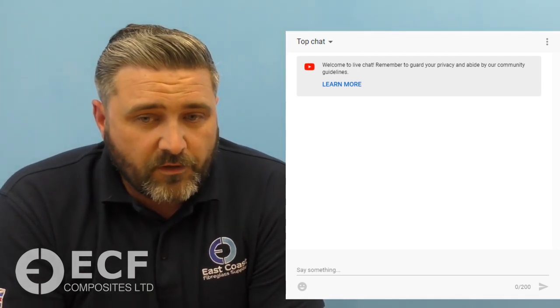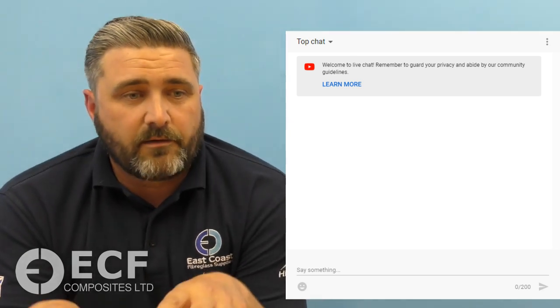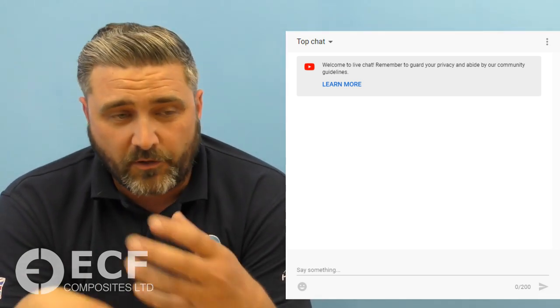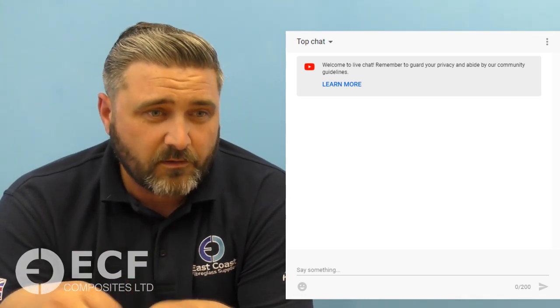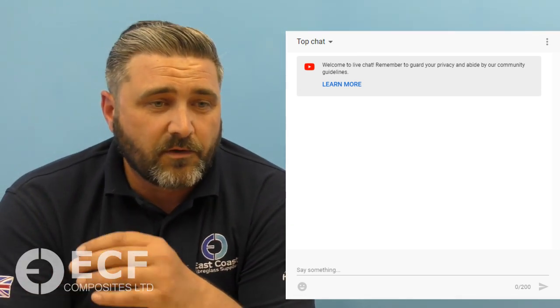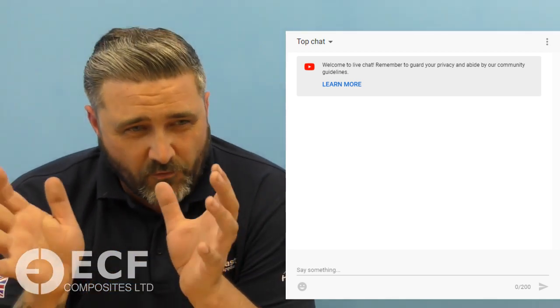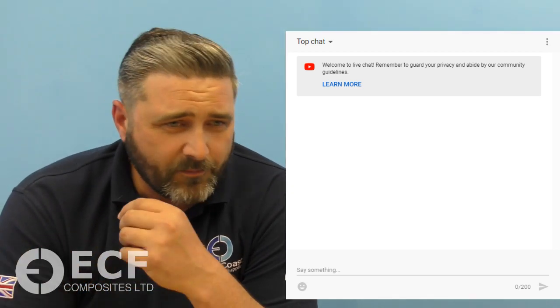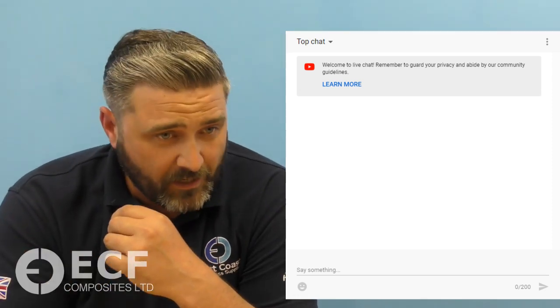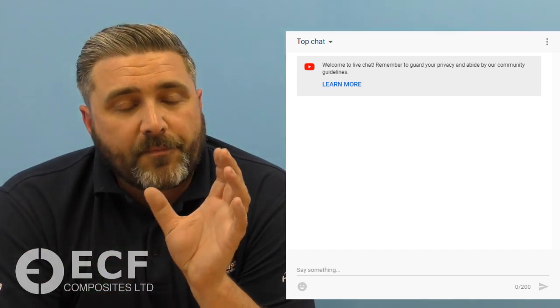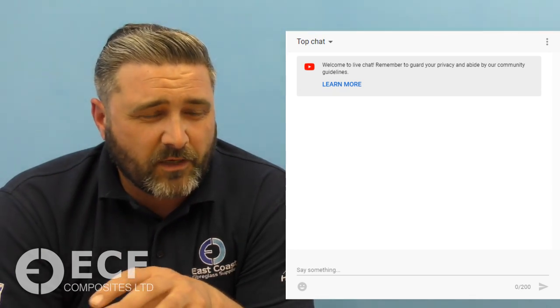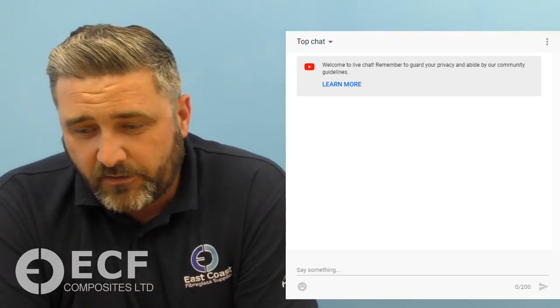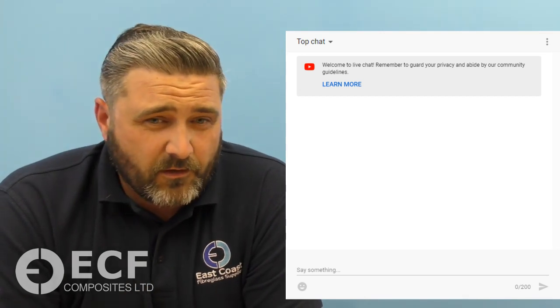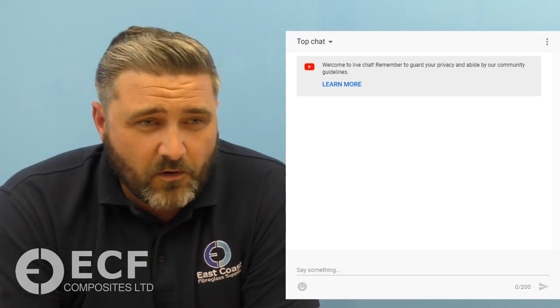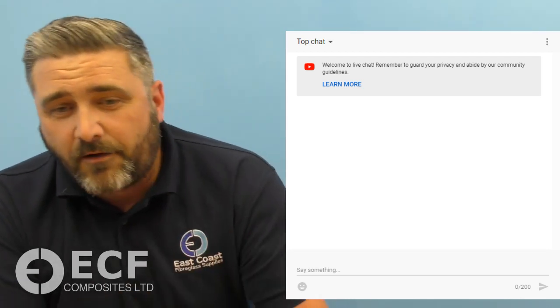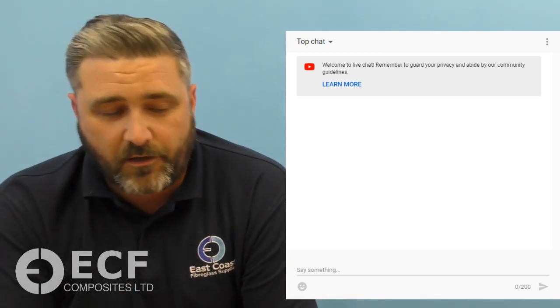Also, if you're going to re-flow coat an area, bear in mind that it is an old laminate. You're not going to get 100% chemical bond between that and an old material. So it's a good idea to give it a really good heavy sanding, wipe it down with acetone to promote some chemical adhesion back, and then go on with a flow coat. But let's say that chemical adhesion is not going to be 100%. That's sometimes why you get a lot of conflicting advice and arguments online on forums. People saying you can re-gel, you can flow coat, other people saying no, you can't.